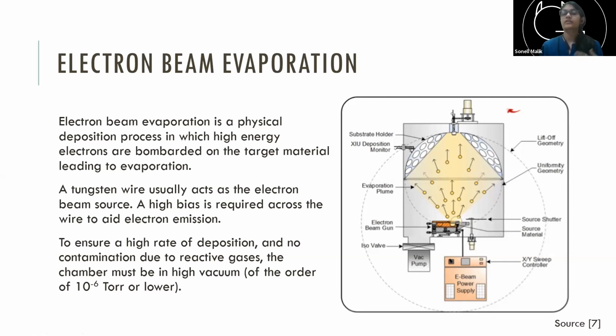And the electron beam evaporation is usually faster. The rate of deposition is also higher. And even in this case, you need your chamber to be in a very high vacuum to not get contamination because of, say, water vapors present or oxygen present or nitrogen or anything that could react to the material that you want to deposit.